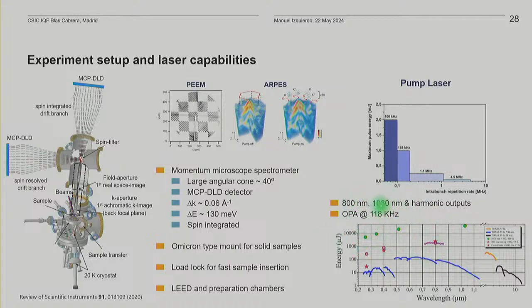And now we are making efforts to make it run at 562 kilohertz, and from there you can go from 200 nanometers to roughly 15 microns. So you could use all this range to excite phonons directly and see how your material reacts to the excitation of phonons. There is also a new add-on that is coming, which is the production of terahertz to use them as a pump.